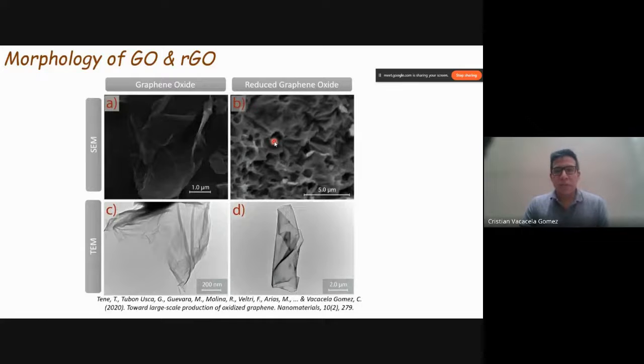But now using another technique, like a transmission electron microscope, we can confirm that the graphene oxide has a corrugated structure, yeah, and after the reduction process, which means that we remove the oxygen functional groups from this graphene, we have a regular structure, a flat sheet, and this corrugated part, for example, is not observed on this type of sample.